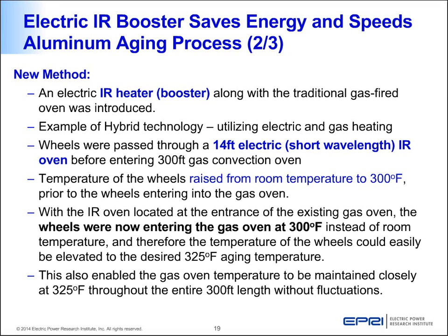After the second step, when the quenching is done, the wheels go back to the ambient room temperature of 70 degrees. The shortwave infrared oven was able to impart heat to the wheels so they can be raised from 70 degree room temperature to approximately 300 plus degrees. Once the wheel is over 300 degrees, it is passed through the existing 300 feet gas oven, and it was able to age at the required 325 degrees Fahrenheit, and all this was happening in just one pass instead of going into the second pass.